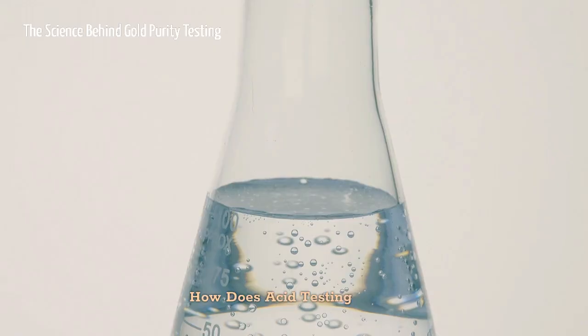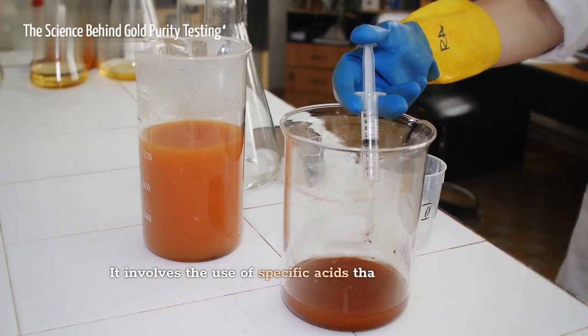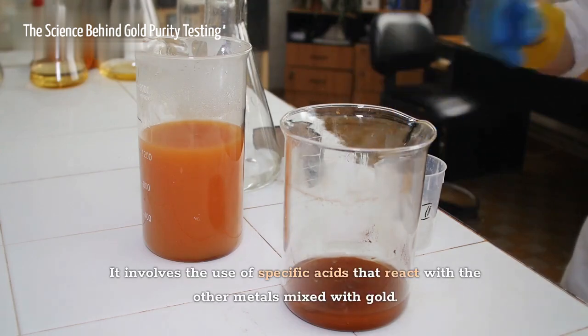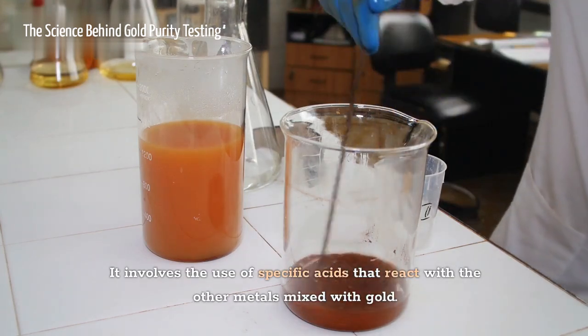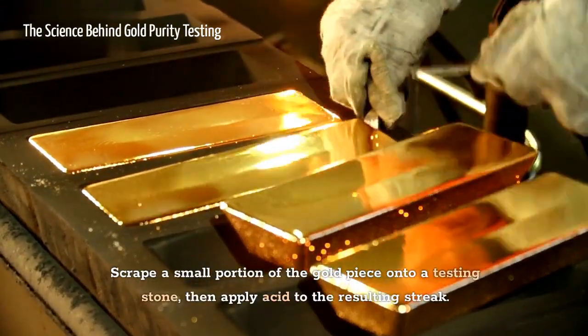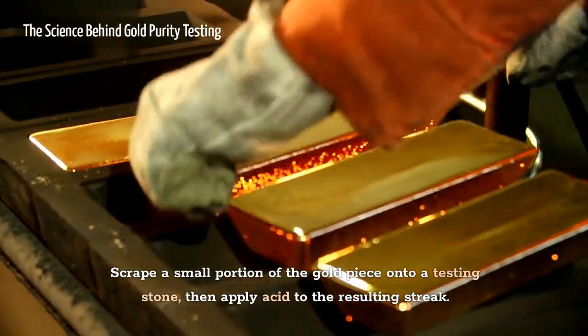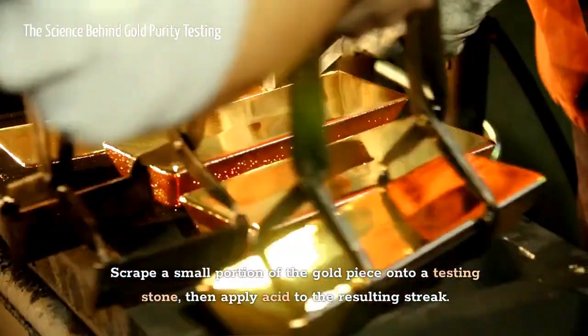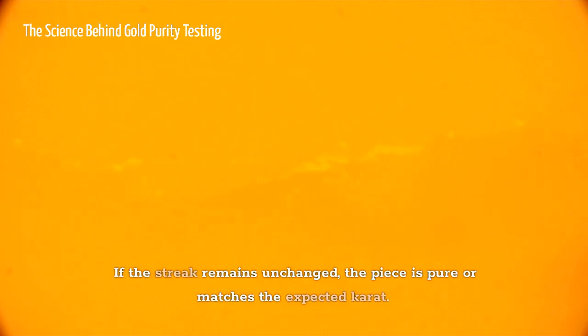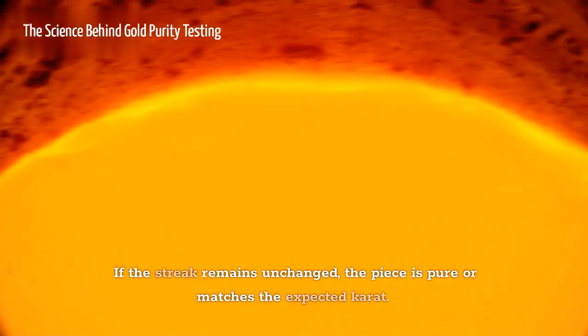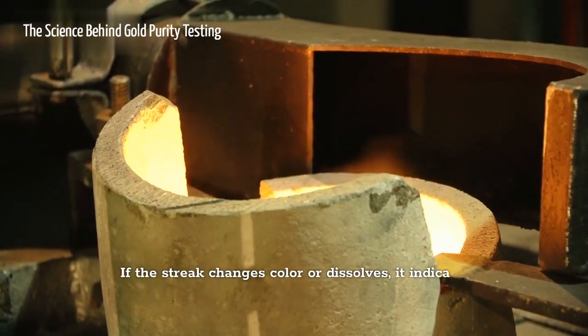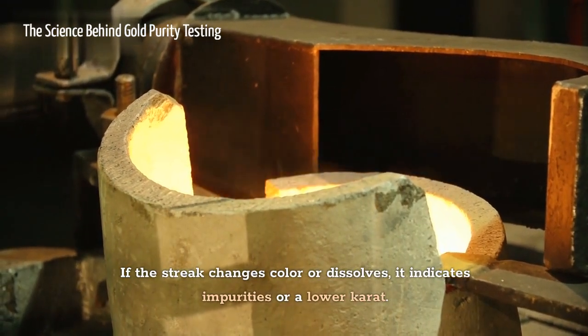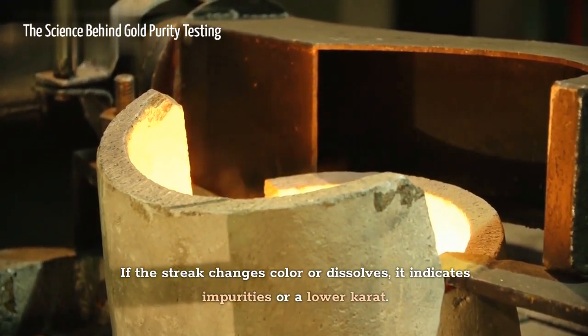Acid testing. How does acid testing work? It involves the use of specific acids that react with the other metals mixed with gold. Scrape a small portion of the gold piece onto a testing stone, then apply acid to the resulting streak. If the streak remains unchanged, the piece is pure or matches the expected carat. If the streak changes color or dissolves, it indicates impurities or a lower carat.